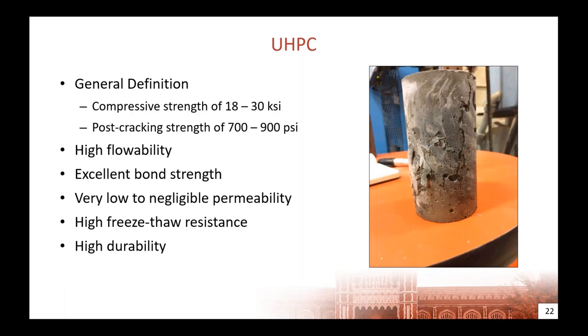And so ultra high performance concrete can generally be defined as a cementitious composite having a compressive strength between 18,000 and 30,000 PSI and having a post-cracking tensile strength of at least 700 to 900 PSI that's provided by steel fibers included in a very dense cementitious matrix. Other organizations will have various definitions of UHPC, but generally it includes having a high flowability, an excellent bond strength with conventional concrete and reinforcing steel, a very low to negligible permeability, high freeze-thaw resistance, and